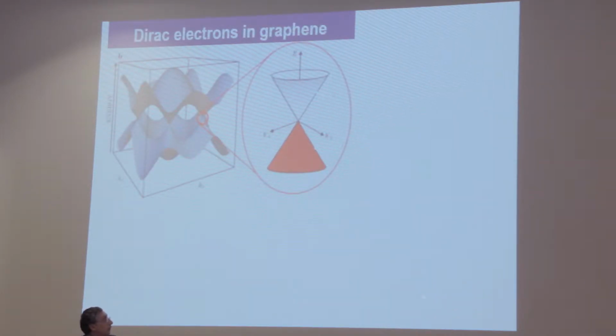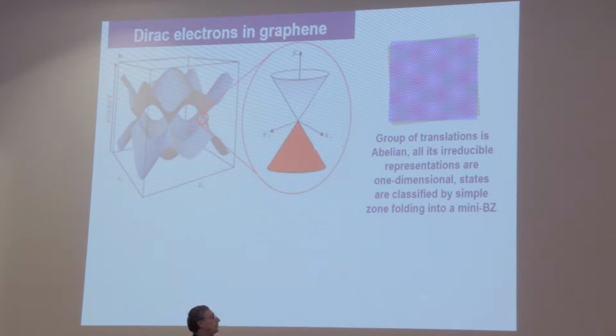To describe electrons in graphene, we use the fact that the Moiré period is long, so that we describe electrons in graphene not starting with the lattice model. We describe them in terms of the Dirac electrons in this two-dimensional material. And we have to keep in mind that for these Dirac electrons, now moving in the presence of a periodic potential, one can use all that is written in textbooks about waves in periodic media, in particular that the group of translations is abelian, and its irreducible representations are one-dimensional, and this makes it very easy to describe the states in the system for Dirac electrons taken in one of the Brillouin zone corners and one of the graphene valleys, K, and similarly in the minus K valley.